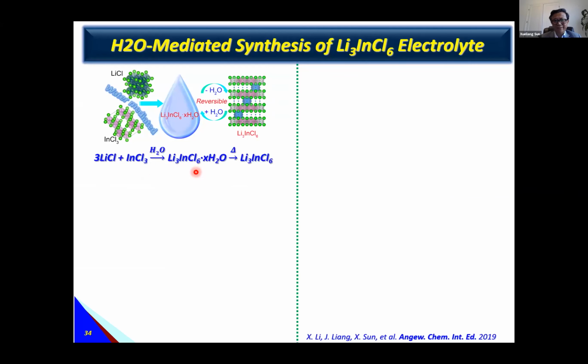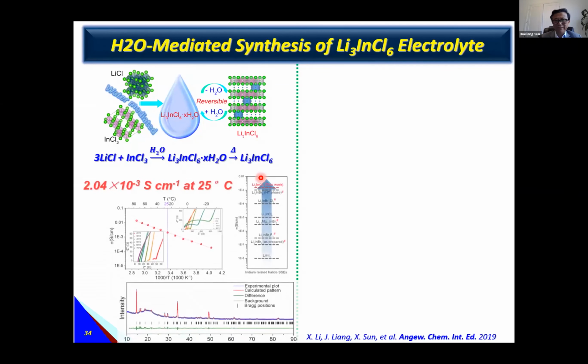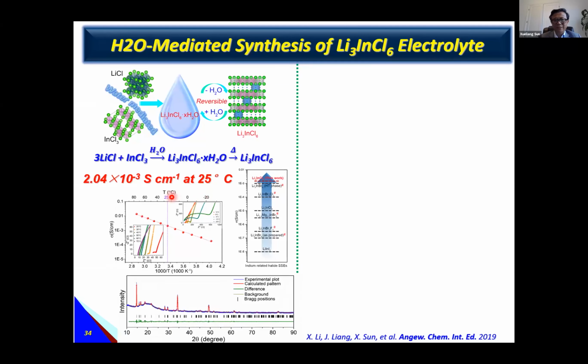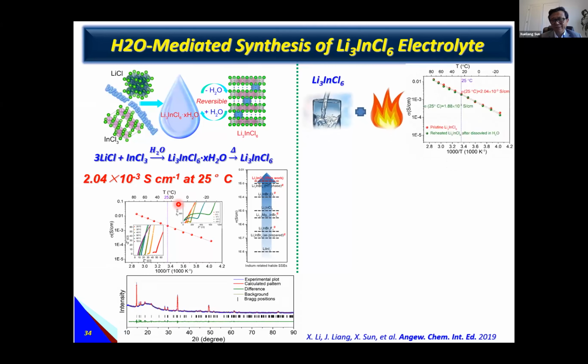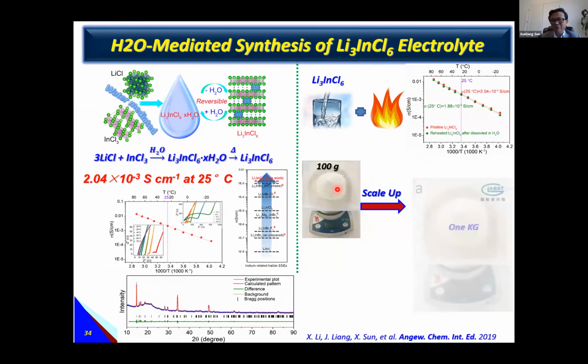After the reaction, we remove the water, and then we can get, at room temperature, up to 10 to the minus 3 ionic conductivity. Interestingly, we found that when we put this solid-state electrolyte back in water and heat it again, there is no change in ionic conductivity. So at that moment we had 100 grams, but now we have a kilogram scale for this solid-state electrolyte.